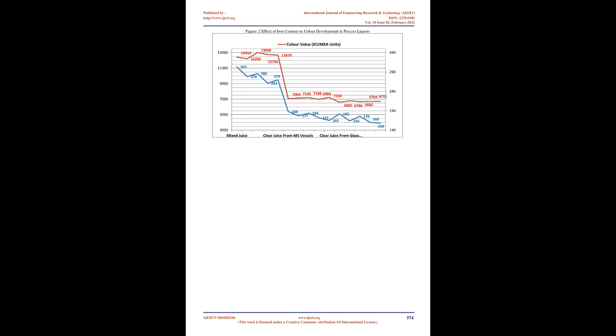Further, there is a definite relationship between iron content in the process liquors and ultimate color development. Since corrosion increases iron content in the process liquors, which reacts with polyphenols present therein, it is expected that there will be substantial color development owing to this reaction, which may alone increase the color values of sugar by 5 to 7% or even more depending upon the iron content and polyphenols present. As such, preventive measures need to be taken to minimize corrosion of process equipments at various stages so as to restrict iron content of process liquors.